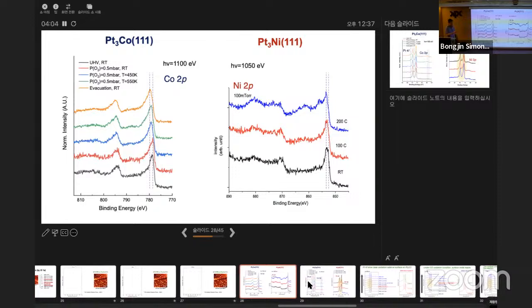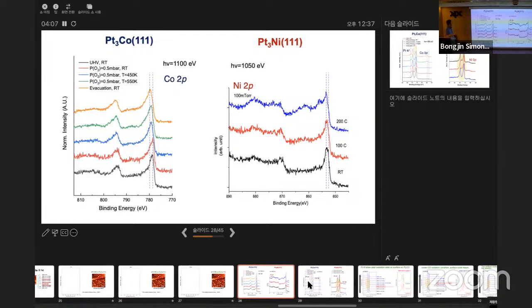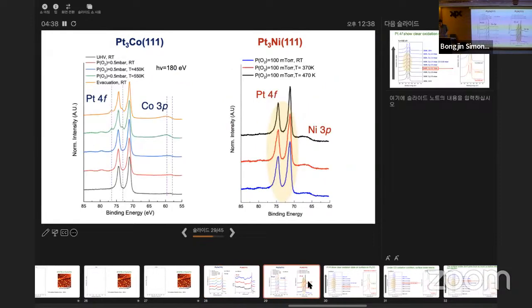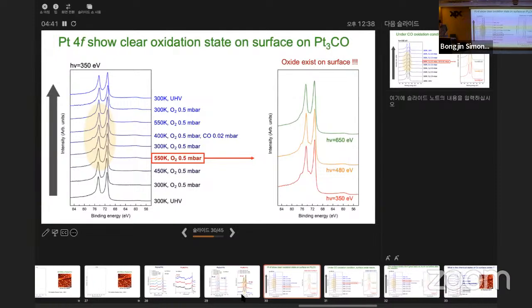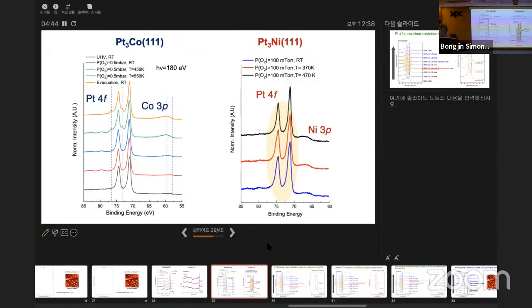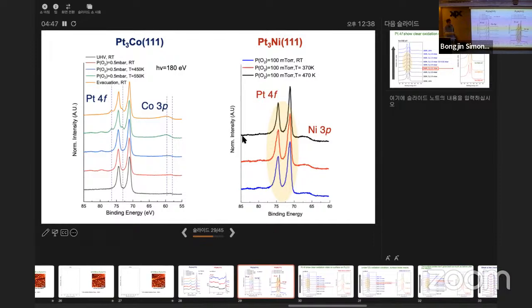If you stop here, when we compare this platinum-3 cobalt and platinum-3 nickel, both 2p state, which is the metallic state of the transition metal, both of them show strong oxidation when you introduce the oxygen. Nickel is similar to cobalt; you can see this oxidation more prominently because this one is shifted quite a lot, and this one also shifted a lot. So in the transition metal, it's clear that it gets oxidized, no doubt. But then this somehow is not following what I actually like.